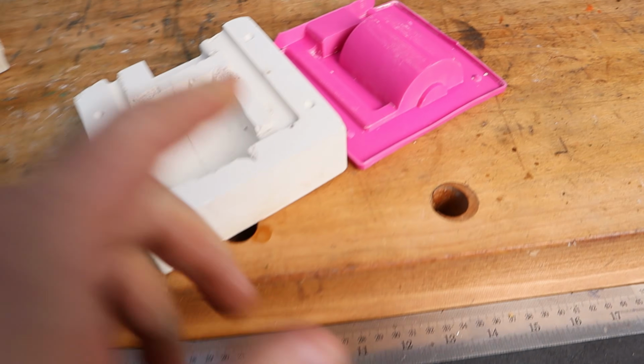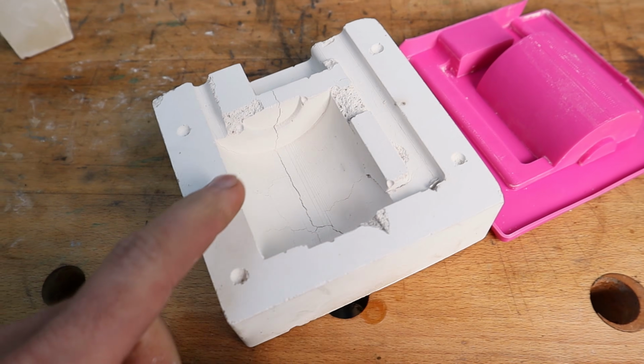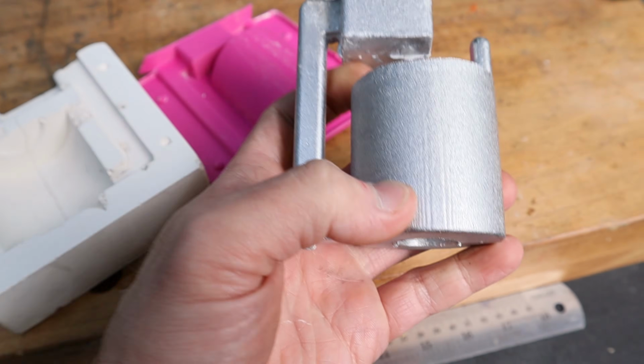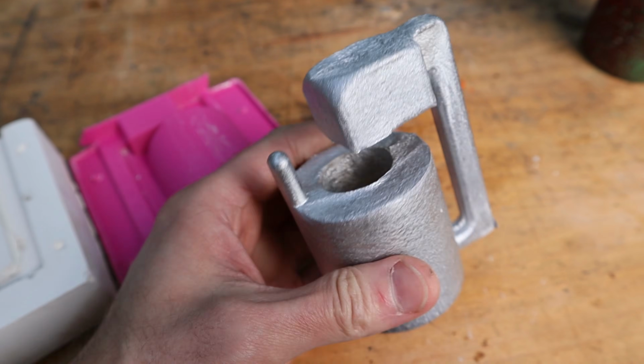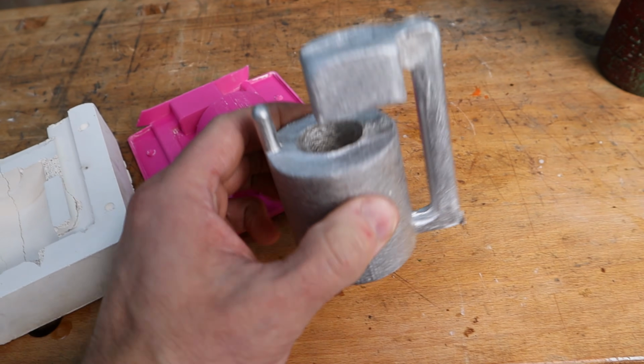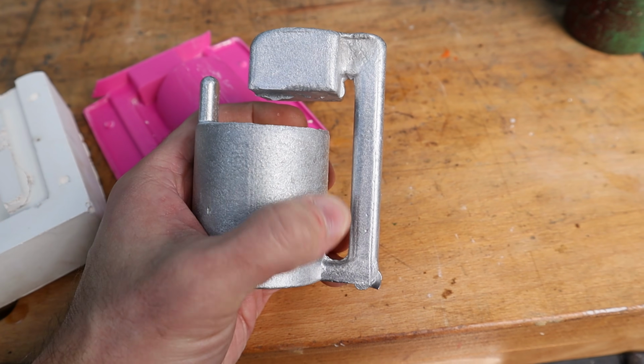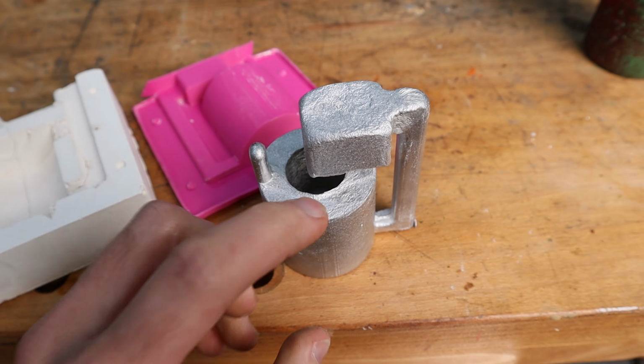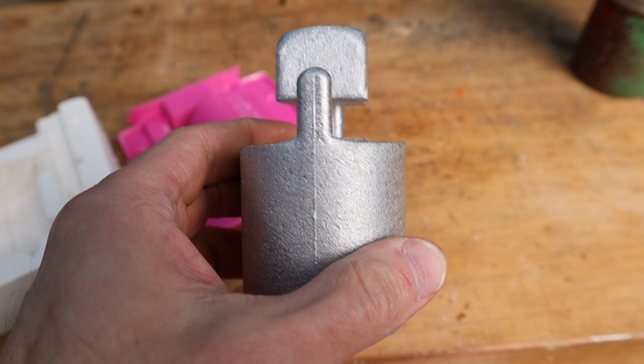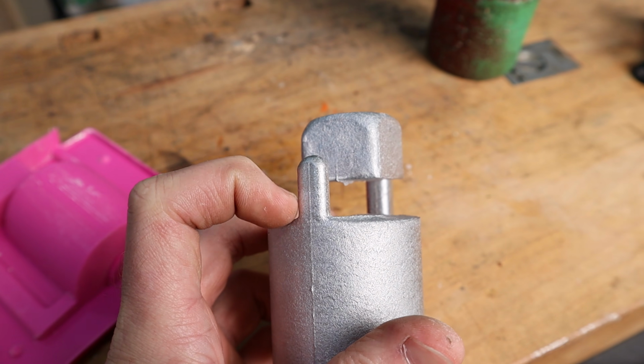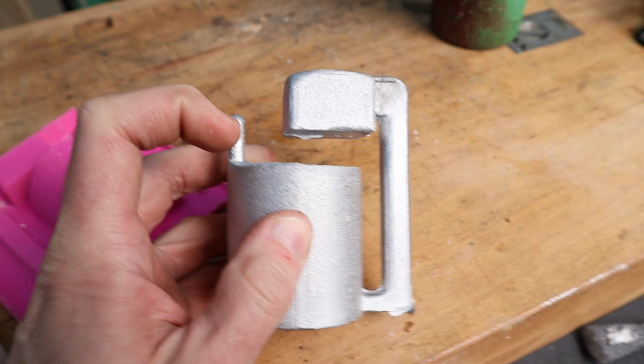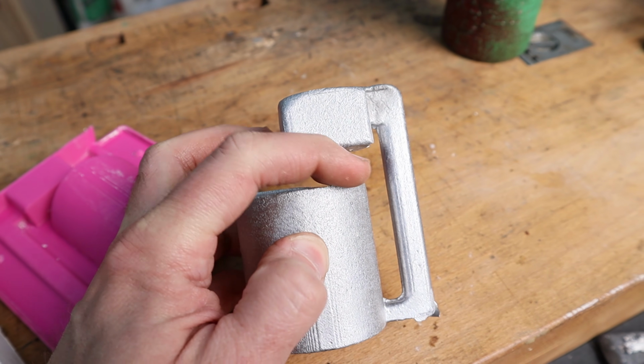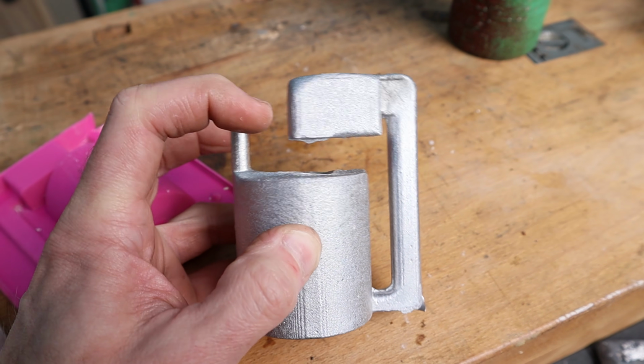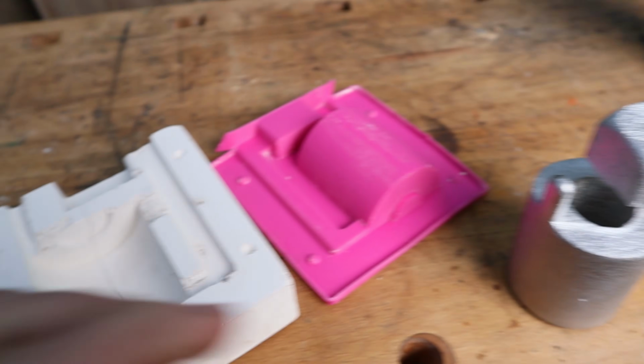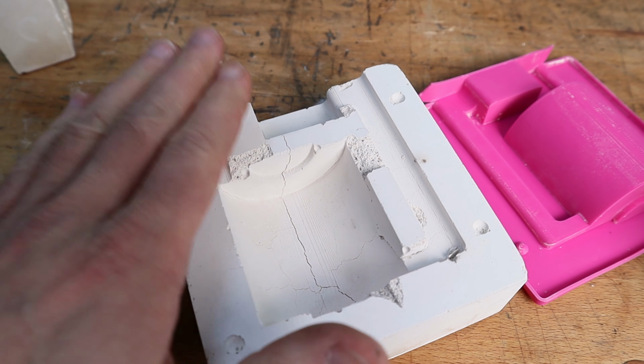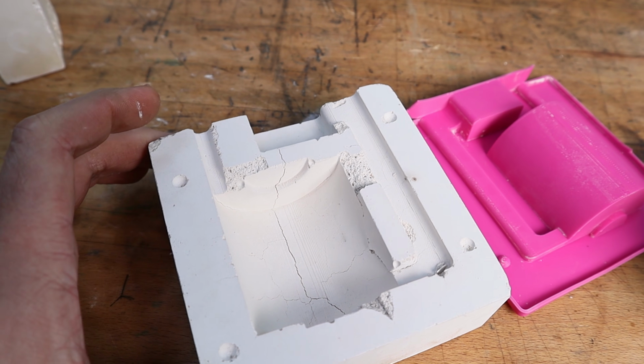And then we went from a PLA print to a plaster mold to our final aluminum part. And it's not like there weren't issues with this. There is definitely room for improvement. This is missing a riser, and I think it needed more vents on the top as well for gases to escape. So if we look here, we have this area that comes up for the vent, but down here on the sides, you can see it dips down where it wasn't being vented properly. So my guess is that we were having some trapped gases in here. And the likely reason for that is because this does not breathe. There's nowhere for the gases to easily escape.